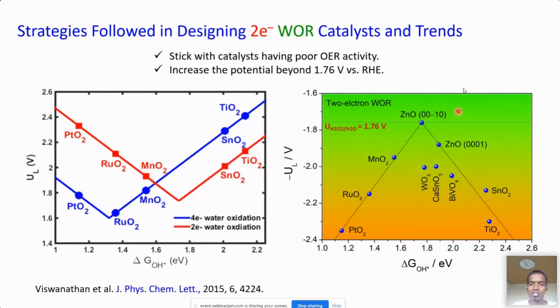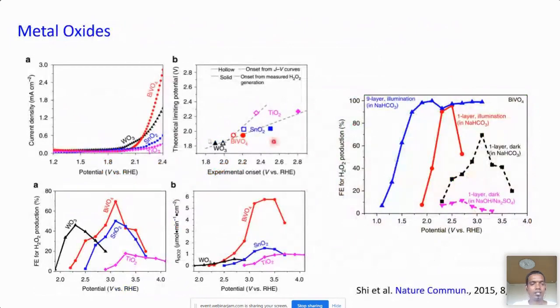These are the catalysts which have been reported to be highly active and highly selective for hydrogen peroxide production through water oxidation. This is a famous example, a very recent report by Shi, published in Nature Communications, where they prepared bismuth vanadate, which performed as a very good electrocatalyst for hydrogen peroxide production. When they applied artificial solar light, it also performed as a very good photoelectrocatalyst for hydrogen peroxide production.